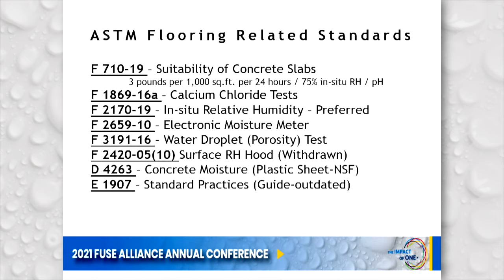There's a test for the use of a surface RH hood, which has been withdrawn, but that hood is something that I use regularly when testing concrete that contains silicates and or if I'm testing the effectiveness of an epoxy membrane mitigation system. We can also see occasionally in specifications D4263, which is the old plastic sheet test. Clearly that does not develop enough information to make any kind of decisions from. And once in a while I still see E1907, which is a set of practices, but it is out of date and should be ignored.